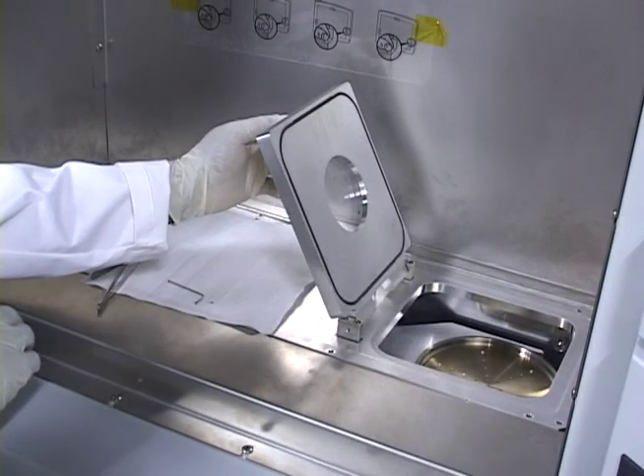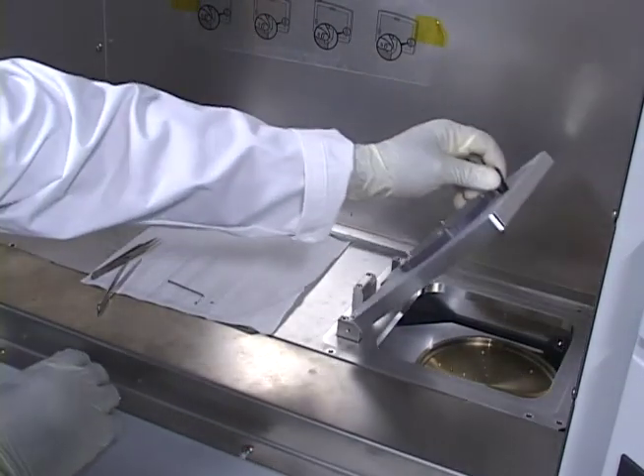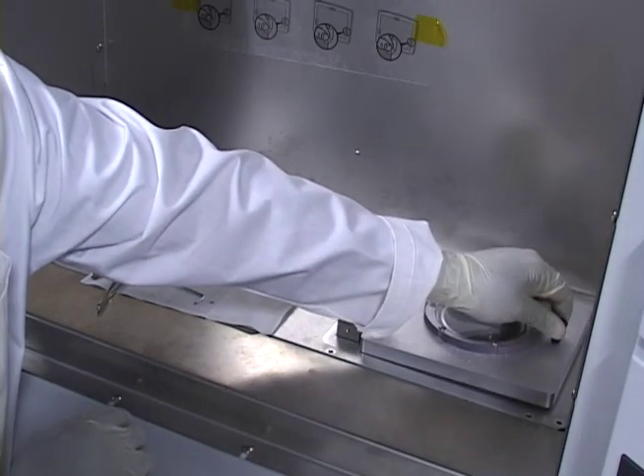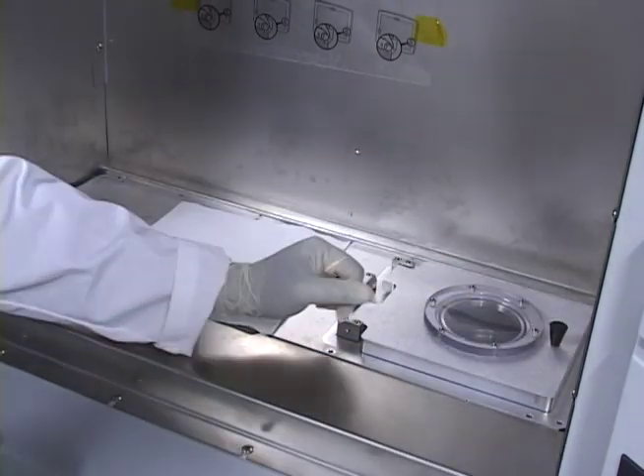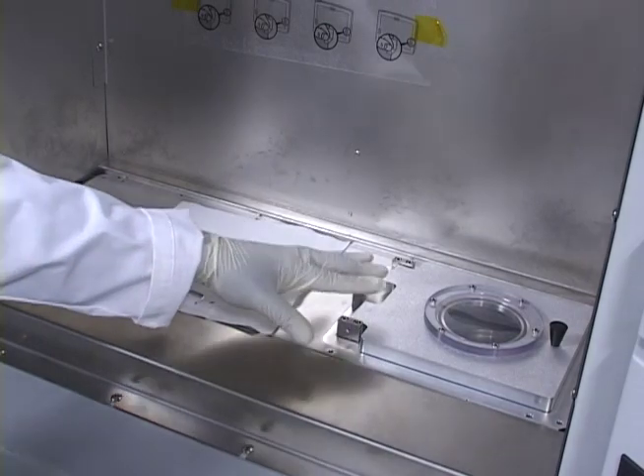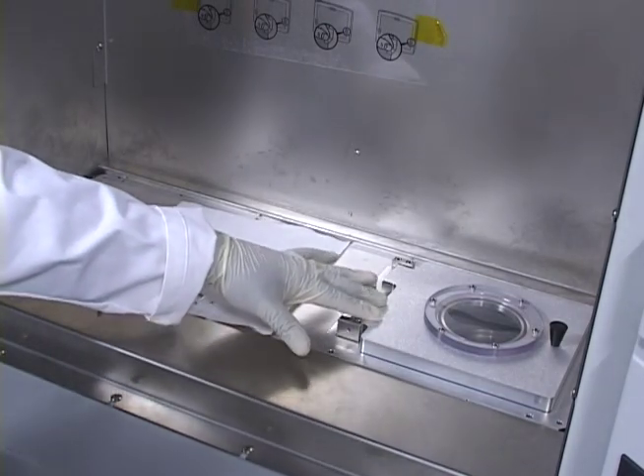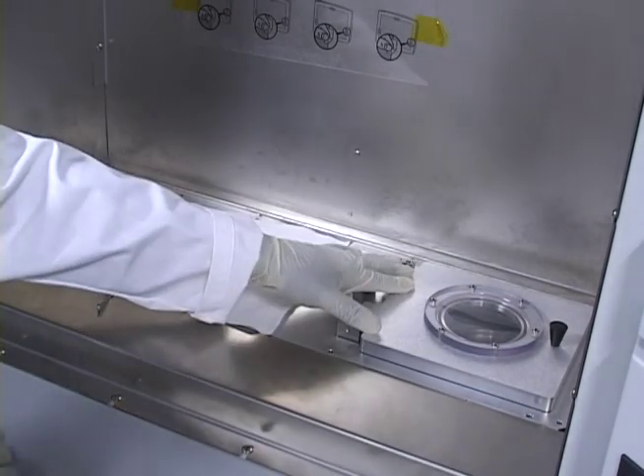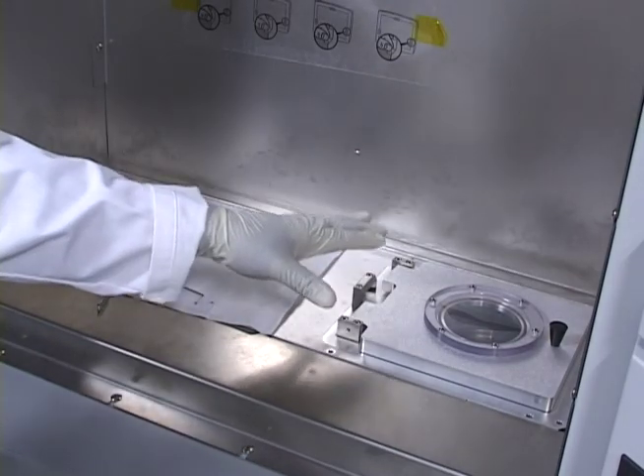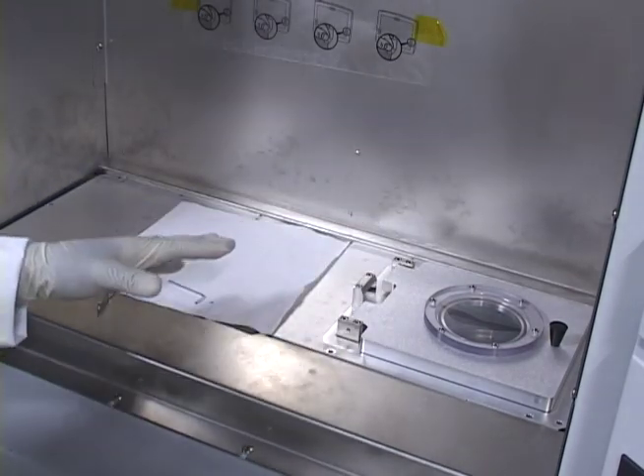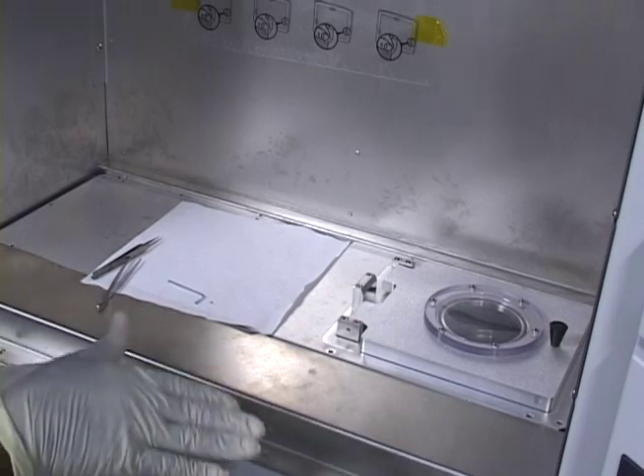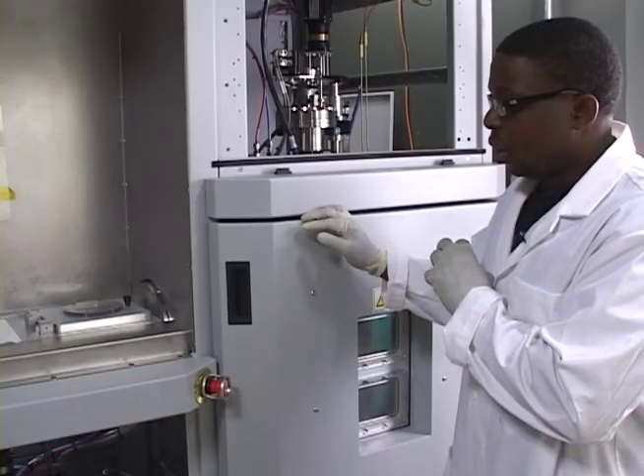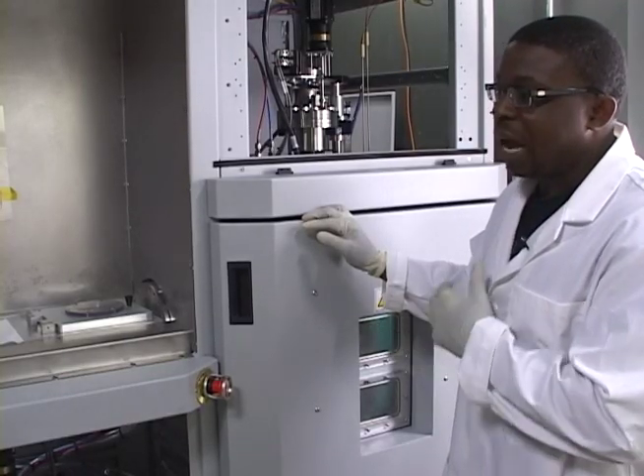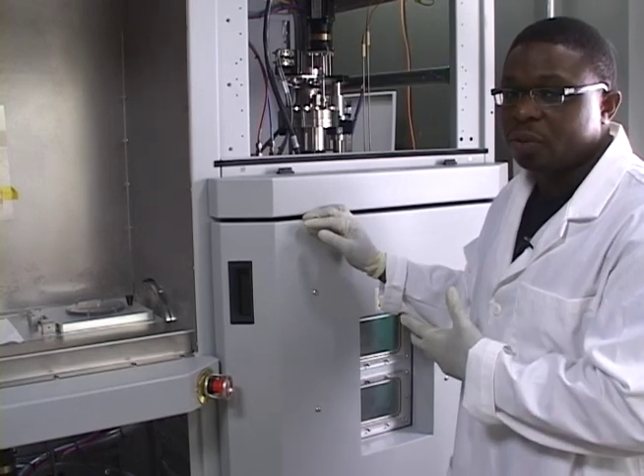It's been inserted into the chamber, and now the door is closed. And this compartment will also be under vacuum. And when the vacuum of this chamber and the adjacent chamber are the same, then the sample will be transferred to the deposition chamber. Now, I will take you through a series of steps on how this mechanism actually works.